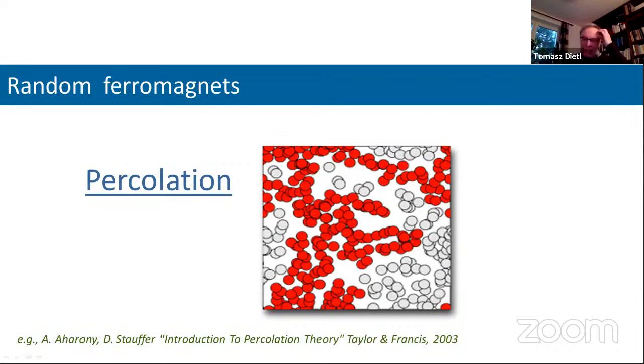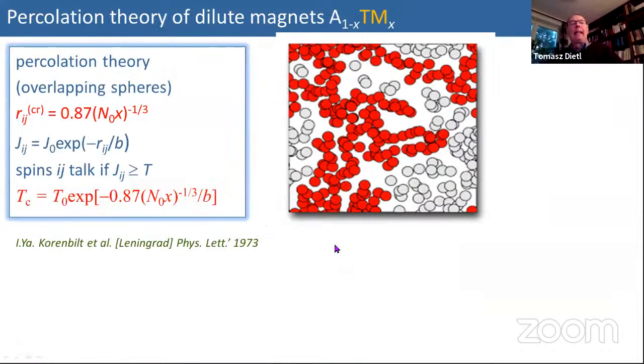Okay, now we have this random ferromagnet, a random distribution of manganese ions, again a very well-known notion for a disordered system, but maybe it's worth recalling in this context percolation. So imagine that you have this short-range interaction, and then you have a ferromagnetic phase transition if you have percolation, if spheres of interaction start to overlap and you form a ferromagnetic cluster. And ferromagnetism in dilute ferromagnetic systems was discussed many years ago.